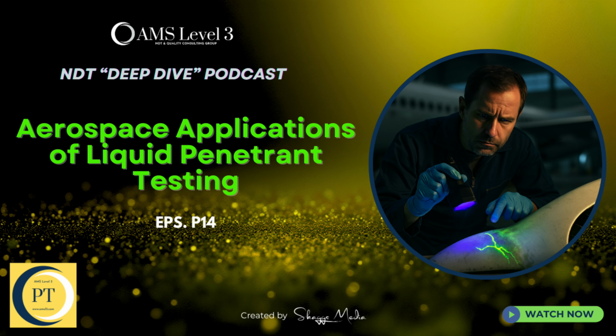So let's start with those periodic checks. What kind of tests are we talking about, and why are they so important for that long-term reliability? They're critical. For water-washable penetrants, for instance, you have to periodically check the water content using a standard method like ASTM D95. Too much water, and the product's effectiveness just tanks. Okay. You also have to verify the penetrant sensitivity and its fluorescent brightness over time because the dye itself can break down. And of course, the obvious one. All the gauges for pressure and temperature and the crucial light meters for white light and UV radiation in the booth, they have to be calibrated periodically.